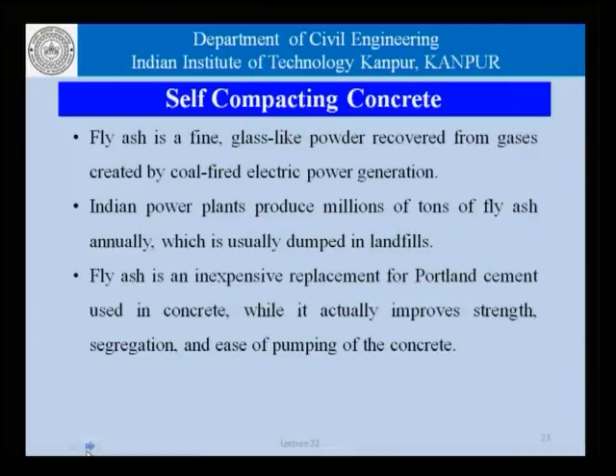It is not only the size and the reactivity and so on, but also the fact that the properties would depend on the coal which is used, the fineness, the burning temperature, and so on. So, if there is a lot of variation in the quality of coal being used in a thermal power plant, the quality of fly ash is also likely to vary. And this variation is one of the reasons why fly ash has not really become an absolute replacement for cement. Sometimes we get very good fly ash, and sometimes we do not get such good quality fly ash.